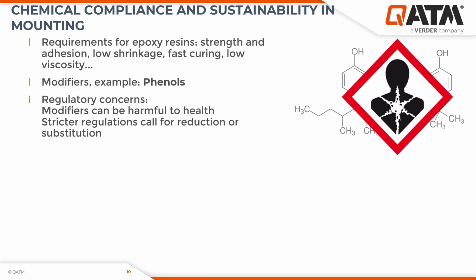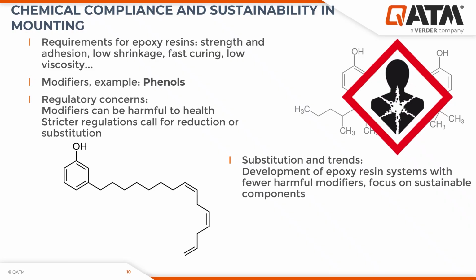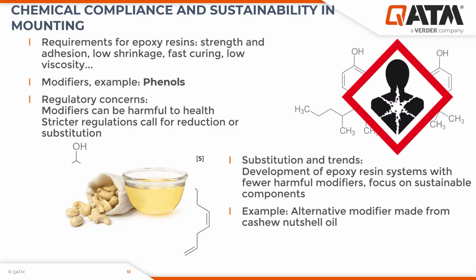A good example is the use of cardanol, which is the substance in the lower left corner. It is a bio-based modifier derived from the cashew nutshell oil, which provides similar properties, albeit with a slightly worse viscosity reduction property. So you need slightly more of cardanol compared to phenol, but keep the overall performance similar without the health risks that might be associated with traditional phenols, which are still used up to date, but these are proper alternatives. You can basically say that consumables are evolving in accordance to chemical compliance and sustainability, which are becoming more important, as well as keeping the technical performance in line, driving the industry towards safer solutions without compromising the consumable quality.